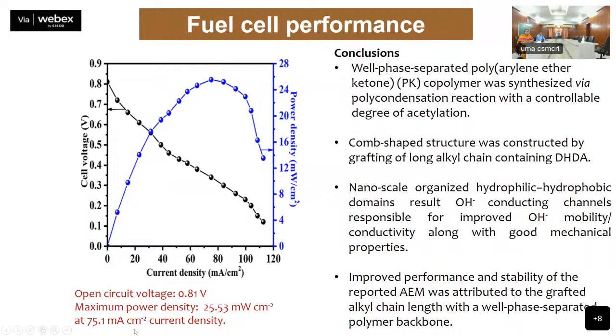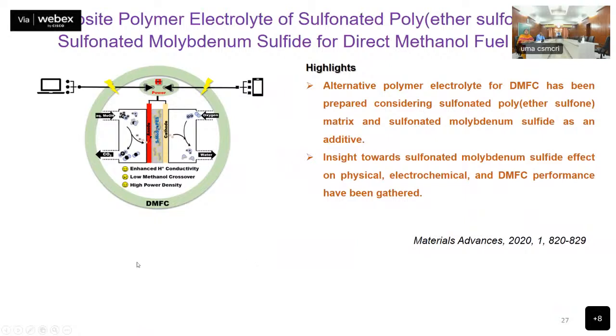You can see that we could achieve 0.81 volt open circuit voltage. And with the long alkyl chain, that membrane is more stable and gives higher results. We have also worked on composite membranes, sulfonated polyether sulfone and sulfonated molybdenum sulfide based composite membranes, for direct methanol fuel cell application.